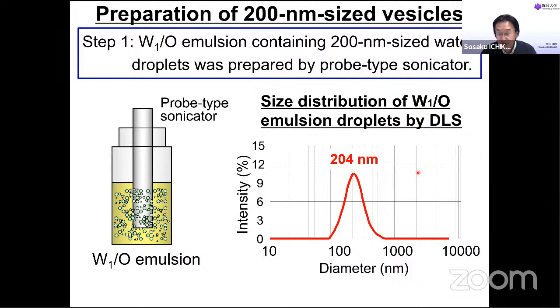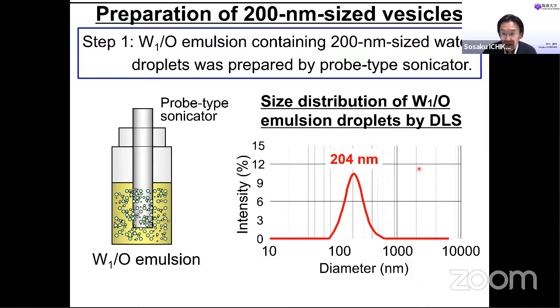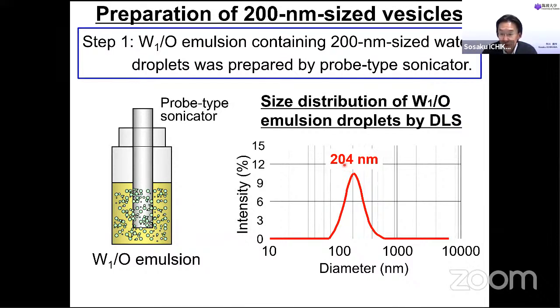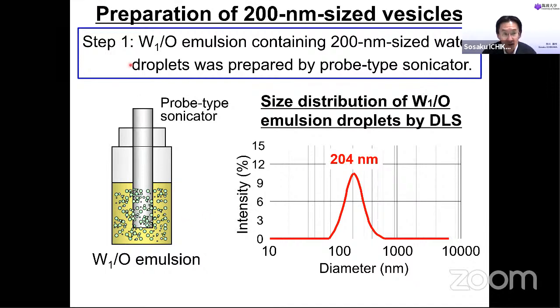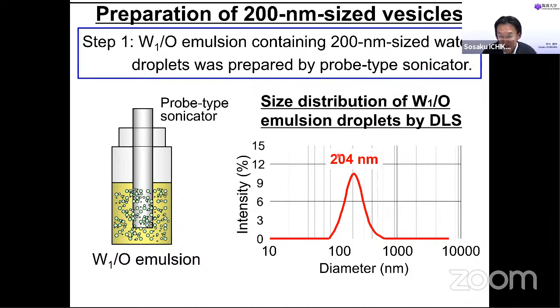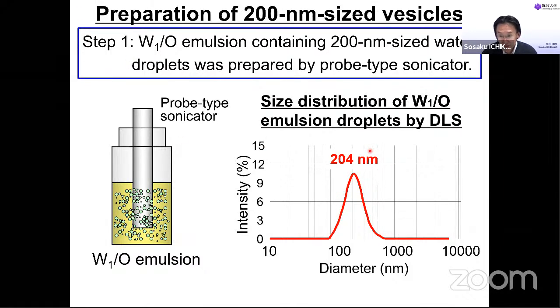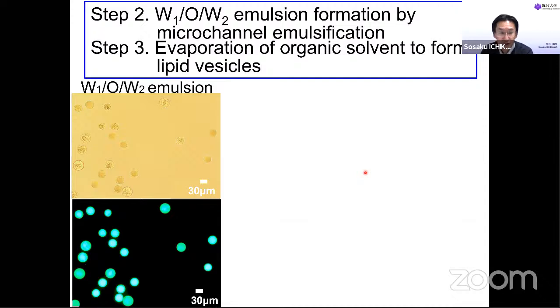This is the size distribution of the initial water droplet. In this case, we prepared around 200 nanometer water droplet at the first step. This is the size of water droplet in the first step. Using this W1/O emulsion, we prepared lipid vesicle following step 2 and step 3.